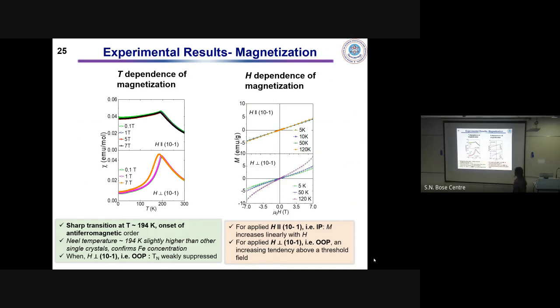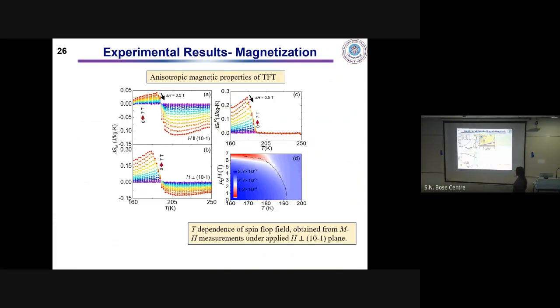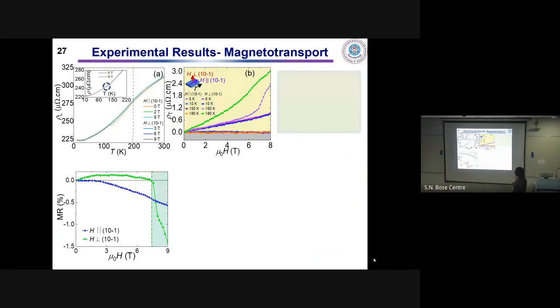From the curve, we took the derivative, and from there we could see that sudden change appeared. Does that appear only at 9 Tesla? Yes, it is only at 9 Tesla, which you have not applied in your magnetization. Yeah. And because of that we confirm that it's probably because of the spin flop happening.